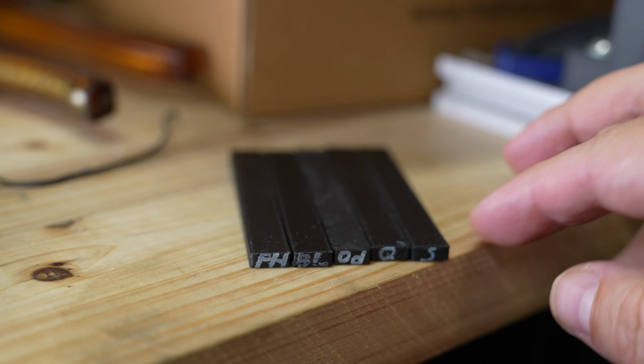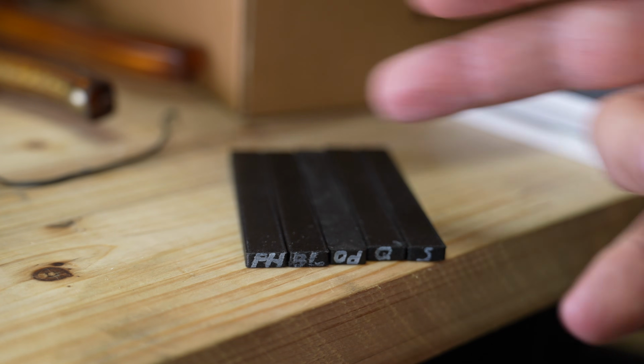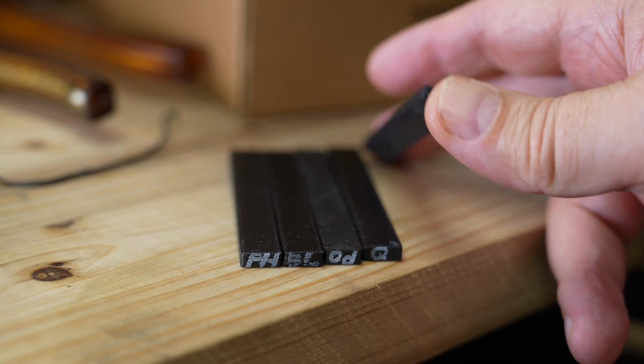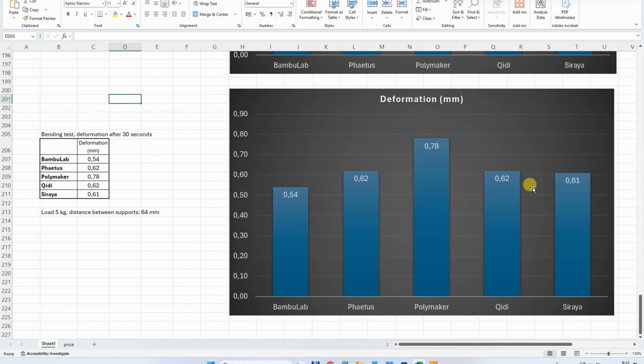This is not a big load for these materials, and I already checked each of them is perfectly straight. And very similar ratio we could see with the creep test. BambuLab has the smallest deformation, Polymaker the biggest, and the rest 3 are very similar.